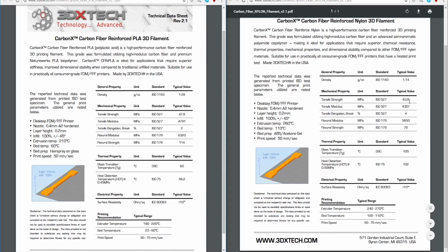Okay, so 47, whoa, nylon, very high tensile strength, also lighter by quite a bit, so about the same thing as the ABS, so quite a bit lighter, higher tensile strength, which is shocking to me. 4,400 for the tensile modulus, 2 times, 5650 for this, a little bit under, and then here is 78, which is quite a bit under this, like 40. Glass transition temperature 105, 102.